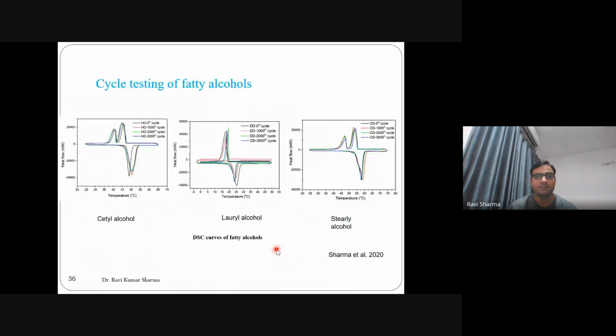We also did thermal cycling of fatty alcohols - cetyl alcohol, lauryl alcohol, stearyl alcohol - using the same setup for 3000 cycles. You can see that even after 3000 cycles, the variation in latent heat and melting temperature is almost negligible. So these are very, very good materials.